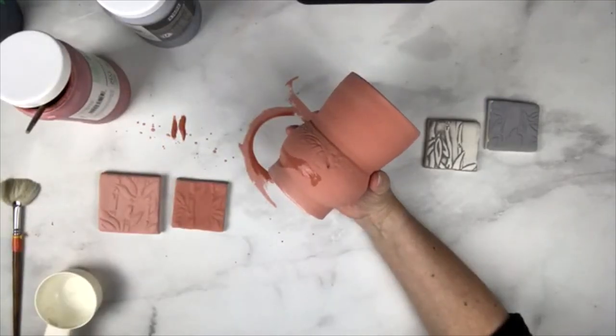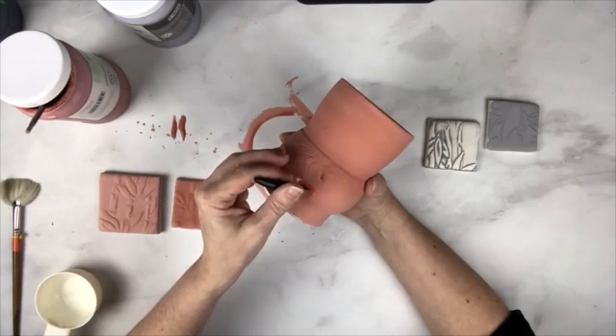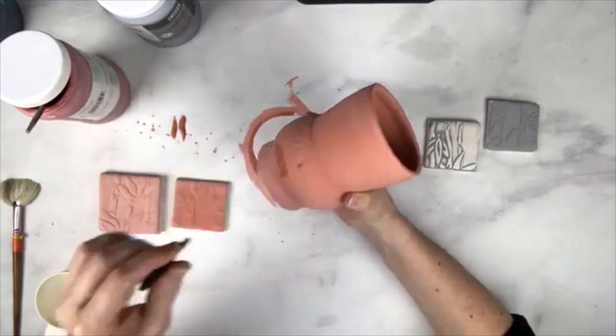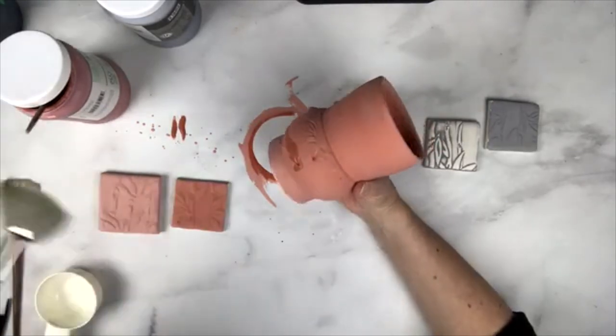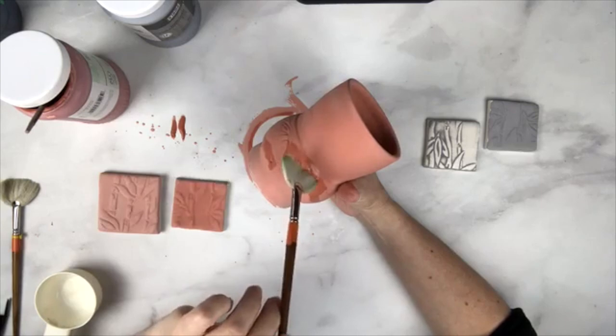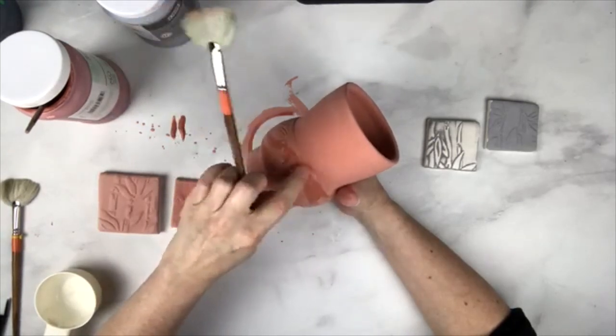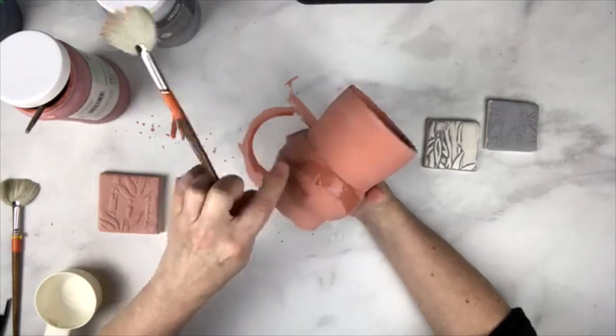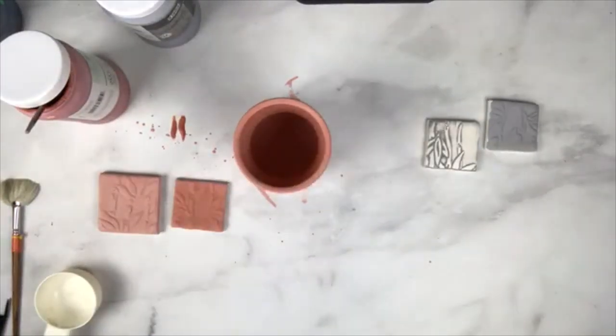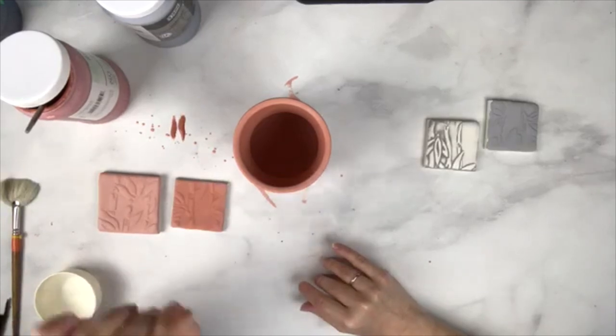I don't have as many tools as I usually do since I'm not at my normal glazing station. You can either try to push it in there, or another way is to water down a little bit of glaze and float it in. Just use a wet brush. You can see little air bubbles rising to the surface. So that is one way. If they're really problematic, I have sometimes re-fired them, and I'll mix a little bit of the glaze with a lot of water to float it into the hole and just kind of work it in there.